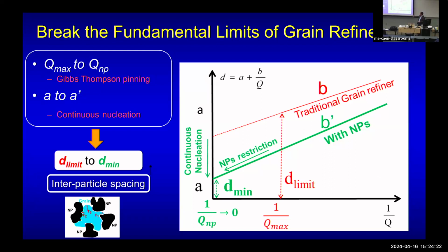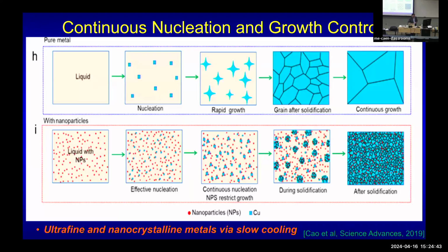But with nanoparticles, they not only provide an infinitely high physical Q, they also allow a lot of nucleation. So you can potentially go to nanoscale. This is the theory: nanoparticle restriction leads to ultrafine grains. Here is the difference. In the traditional free growth theory, you have nucleation, and sometimes we use a grain refiner to get more nuclei. But once they start to grow, they grow so quickly.